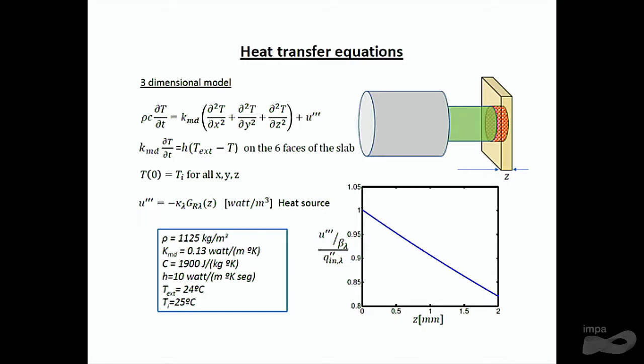And this is the quantity that links the heat transfer equation with the radiative transfer equation. This quantity, that gives you the watts per cubic meter released by the action of the laser on the particles inside the sample, is given by this expression. It varies along the theta direction, as it shows here. This is a normalized quantity, but it's more or less proportional to U3 prime. And this is what they normally call the heat source in the heat transfer equation. Here we have some typical values we're going to use in the next slides to run the simulations.